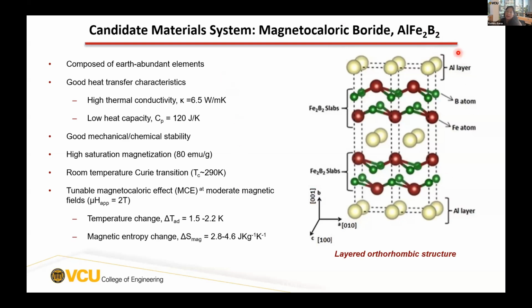Aluminum iron boride is not as good as lanthanum iron silicides, but it shows a moderate magnetocaloric effect, a delta T of around 2.2 Kelvin. You can tune the delta S to 4.6 joules per kg Kelvin at 2 Tesla.